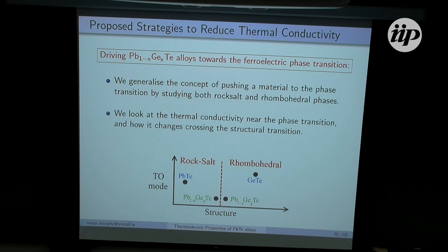Now this expands a bit on what I've previously been talking about, because beforehand, in the case of the lead telluride and lead selenide alloy, we pushed it towards the verge of the phase transition, but we kept things in the rock salt phase. Now in this case, we can actually look at what happens to the thermal conductivity as we undergo that phase transition and see how the thermal conductivity behaves in both the rock salt and the rhombohedral phases of the alloy.